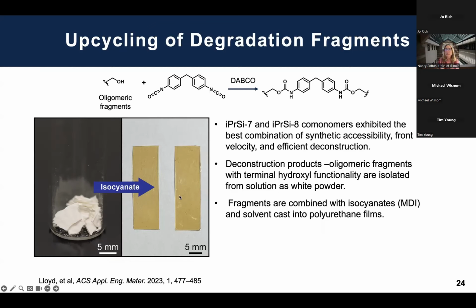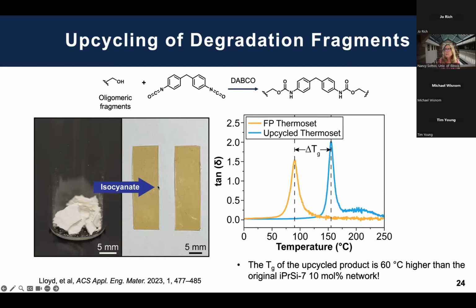Now, this polyurethane is not recyclable, so we've just sort of gone like 3/4 of a cycle, but it's a huge start because this polyurethane, this is the blue curve, this is just the tan delta to show you the Tg.